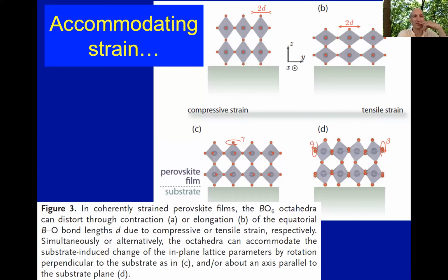I just want to introduce one almost generally valid concept, which is illustrated here: when you grow a material in a compressively strained way, namely such that the lattice spacing of the substrate is smaller than the natural lattice spacing of the bulk material you're interested in, then typically you get a rotation along the c-axis that develops. So the bonds along the c-axis are straight, but you can tune with compressive strain the in-plane metal-oxygen-metal angles, which, as we'll see tomorrow, will have direct influence on the bandwidth.